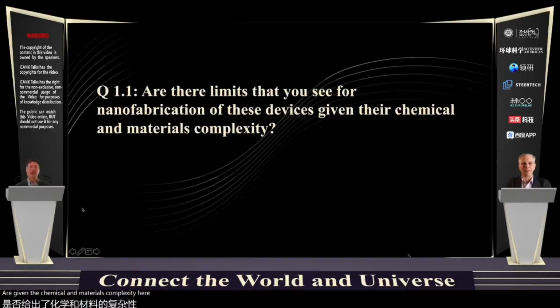Very good question. We made a 2 nanometer thick device, trying to see the physical limit. The thinnest we could make was 2 nanometers, and we found it works. I personally believe that even when we can make 1 unit cell, which is 6 angstrom, it should work as well. So I see the limit is probably 1 unit cell.